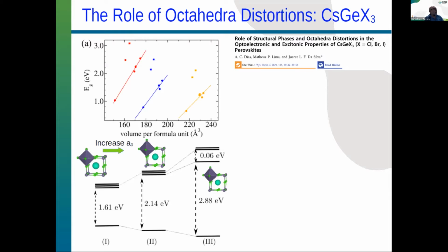And then you got a band gap of 2.14, which gives us an idea of how the band gap changes when you increase the volume, okay? And this is very important. First, the distortion of the octahedron creates an increase in the volume effect, which increases the band gap. After that, we have a distortion of the octahedron that's responsible for breaking the symmetry and gives an additional increase. This happened in particular for this cesium compound here.